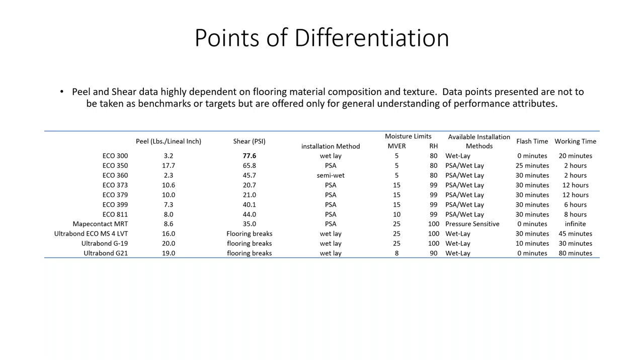Another good product. Again, old school technology, good peel, good shear numbers, a PSA installation method, but a limited moisture vapor emission rate of 5 pounds and 80%. These are legitimate numbers. You don't want to use 350 on anything that's hotter than those numbers. It just wasn't designed for those kinds of attributes when it came out 20 years ago. So it's something to keep in mind. 360, same kind of story. Again, a transitional phase changing material, if you want to call it that, with reasonable peel strength and very good shear strength. This one goes in ideally as a semi-wet insulation method, so it requires porosity. But again, it's a limited moisture vapor emission rate deal.